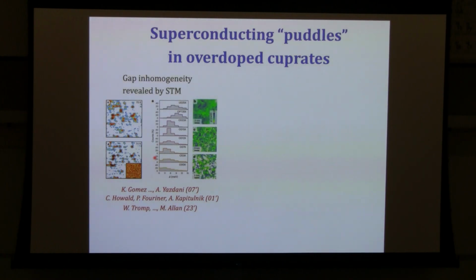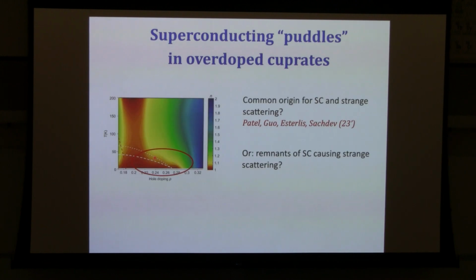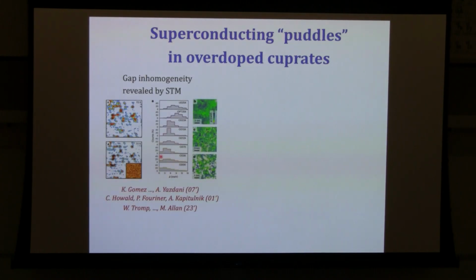Well, there's good experimental evidence that in the overdoped cuprates, throughout this doping regime, even when you suppress superconductivity, for instance if you just heat up the sample above Tc, superconductivity is actually not destroyed everywhere. There are a lot of different pieces of evidence from experiments leading to this. The most direct one is STM. By doing scanning tunneling microscopy, you can measure the local gap in the electronic spectrum that you can associate with superconductivity. And these are older experiments by Ali Yazdani.